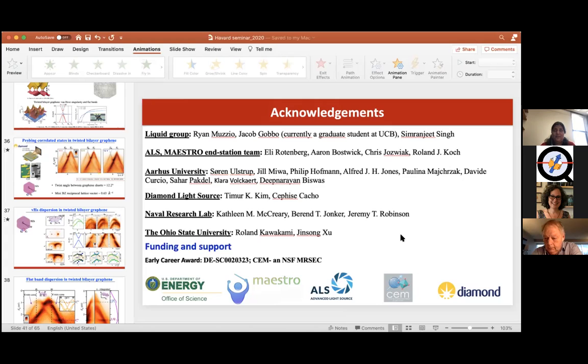But recently, we actually have beam time next week, and today my students are shipping really air sensitive material, which is sodium bismuth, which we cannot even take out in the glove box. So it's that air sensitive. So in order to measure their ARPES spectra, we're shipping a UHV suitcase. The samples are in a UHV suitcase, and today my student is supposed to ship them. It has a small ion pump backed by a battery pack, and once they receive it, they are going to attach it to the beamline directly and basically just measure them.